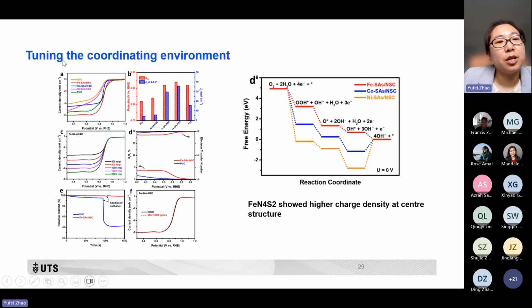When we use this material for ORR, we can see the iron one with the atomic structure of iron, nitrogen 4, sulfur 2 shows the best performance compared to the cobalt and nickel ones. It's a 4 electron process to produce water as the product. Also, it shows very high methanol tolerance and stability here.